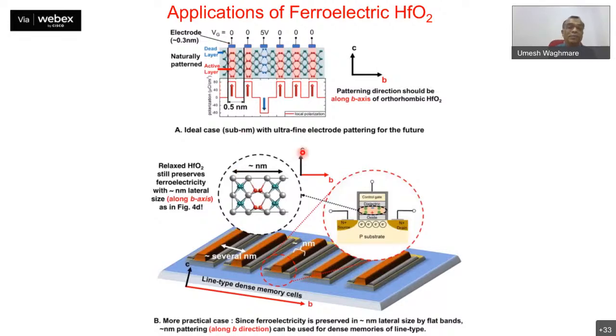And even if you say with the presently developed deposition technologies, one may have to have several nanometers of width, sure, this is still a 100 times growth in the density of data storage that one can achieve using ferroelectric oxide. Of course, there are still challenges to tackle, and this is sort of just the beginning. As you know, when a material is realized with some interesting property, to deploy it in technology takes a lot of time. And translation into realistic application always takes time.